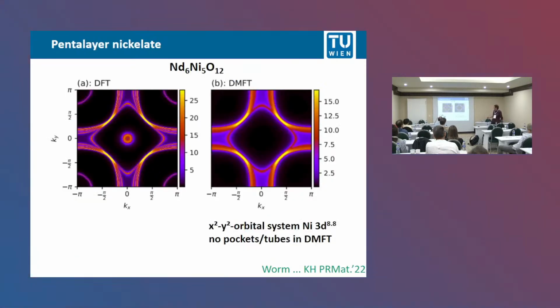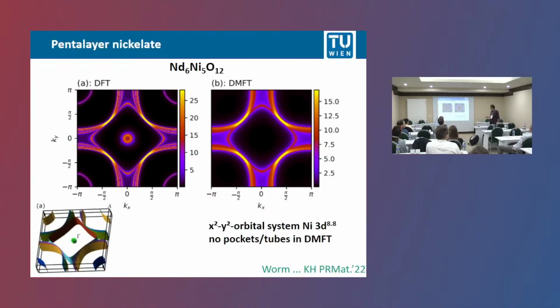But of course, the 5-layer system now has 5 surfaces. In DFT, you still have pockets. In DMFT, the pockets are gone. And as the pockets are gone, if you have these 5-layer films, you can do the algebra, then you have a filling of 1/5 or 20%.